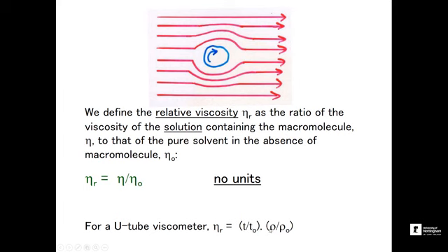But for low concentration work, especially for polysaccharides, which are very viscous, you don't need to have high concentrations to make measurements, then the density correction becomes very small. So for very viscous solutions, you don't have to worry about density corrections because you work at low concentrations. But for protein work, generally, we need that correction.